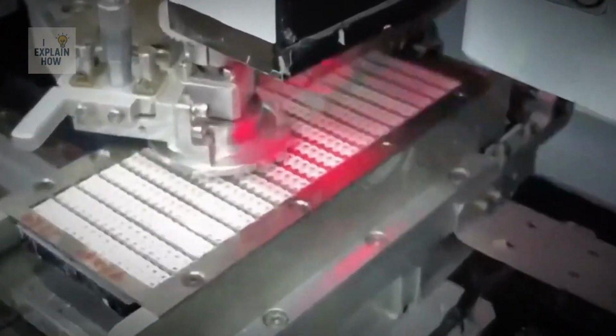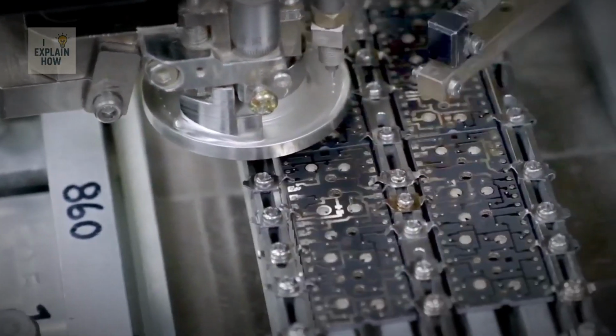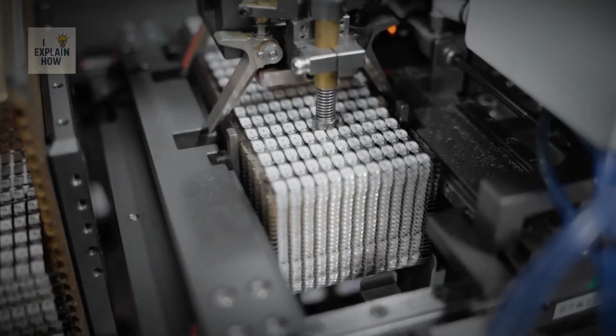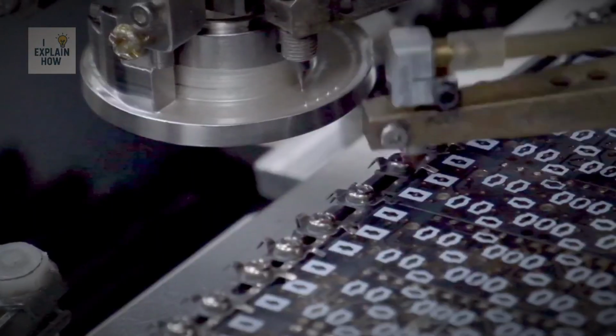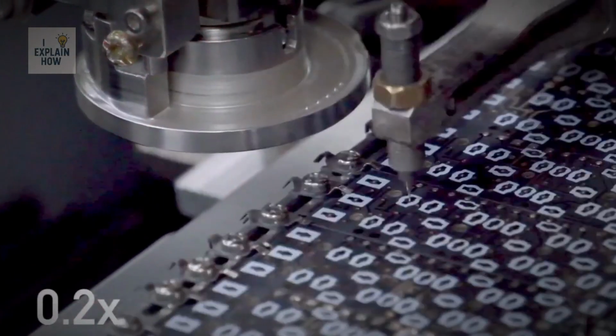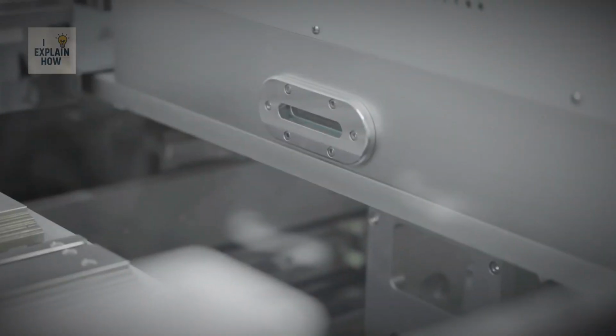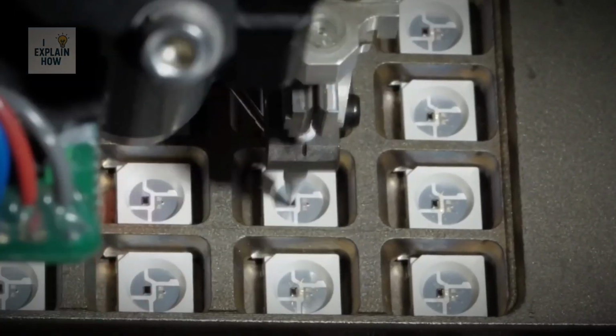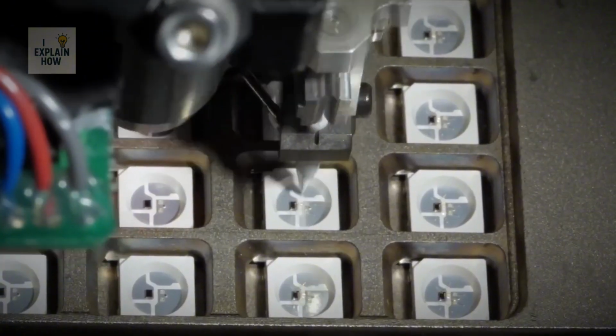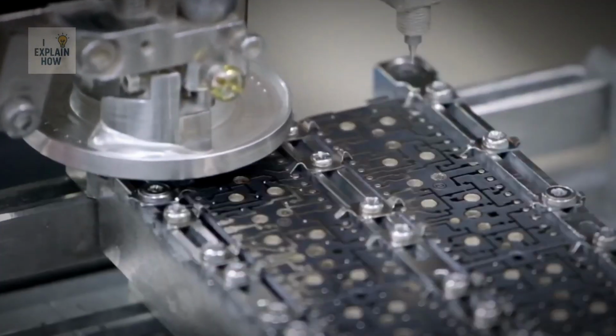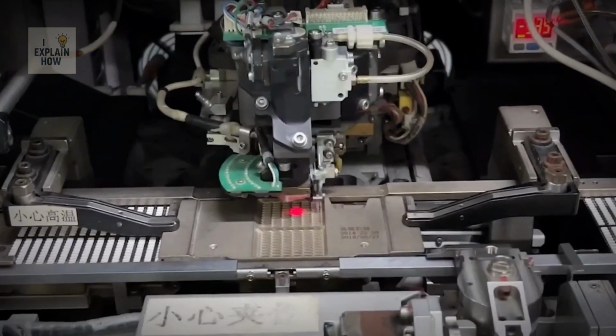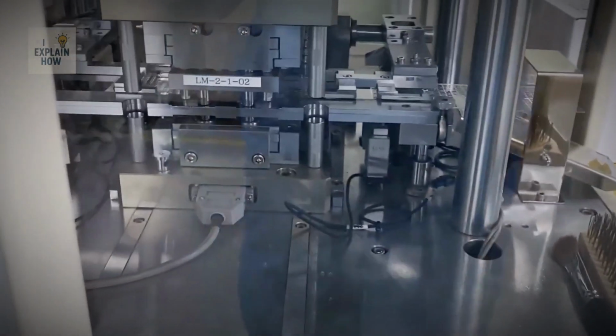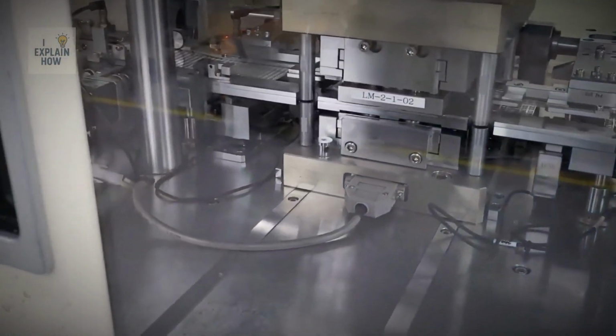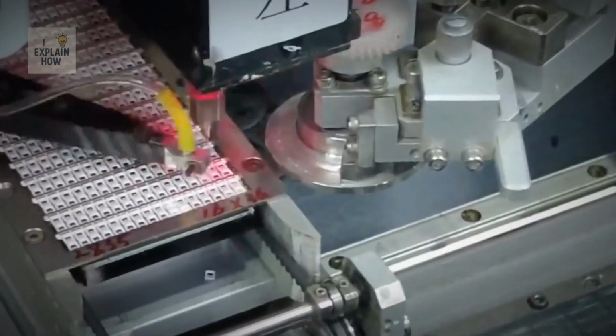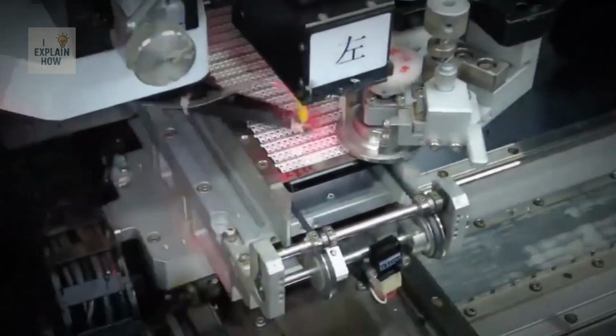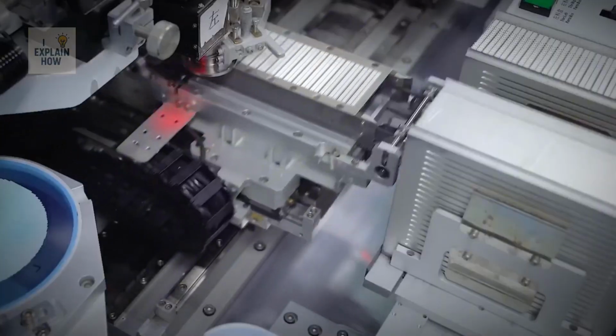It securely anchors the chip in place while providing an efficient path for heat dissipation. The expanded film carrying the separated chips is then fed into the machine. Industrial vision cameras scan the entire surface, automatically identifying the exact coordinates of each chip as well as the metal pads on the conductive frame. The robotic arm operates at near instantaneous speed. Pick up, rotate, align, and place, each cycle taking only fractions of milliseconds. Precision at this stage is critical. Misalignment of just 20 to 30 micrometers can cause color shift, reduce LED lifespan, or even lead to immediate failure.